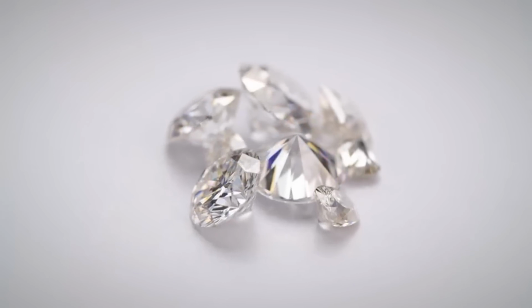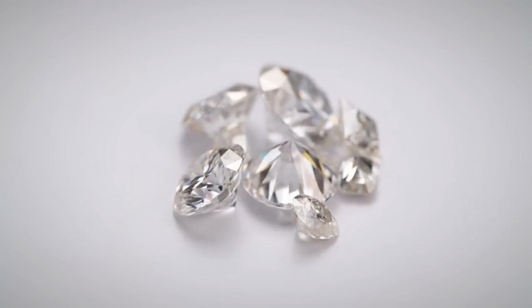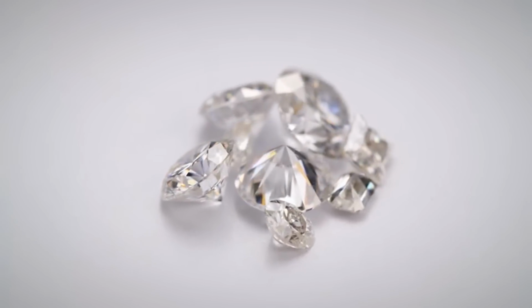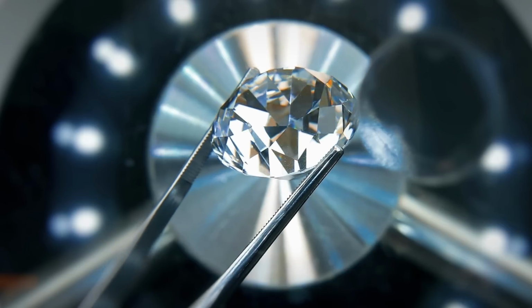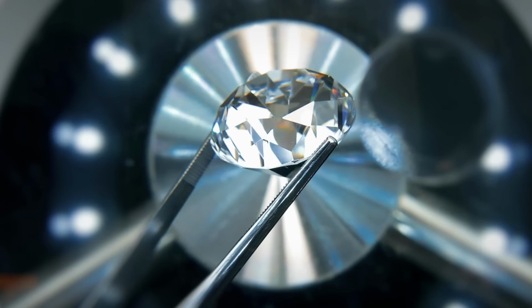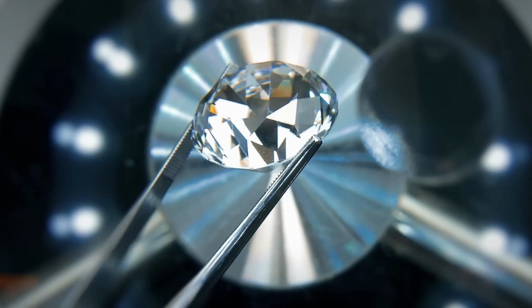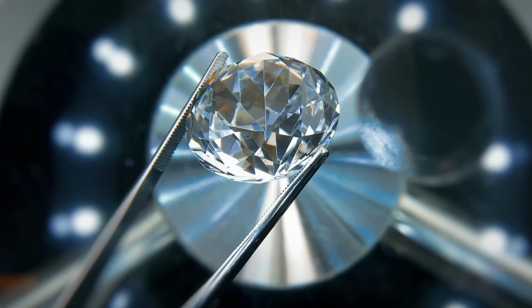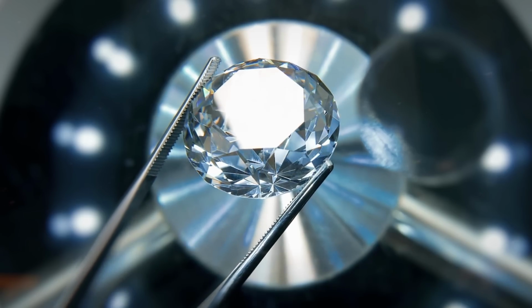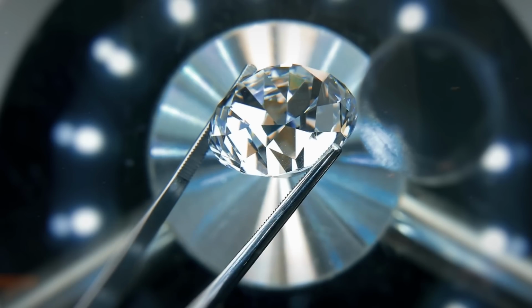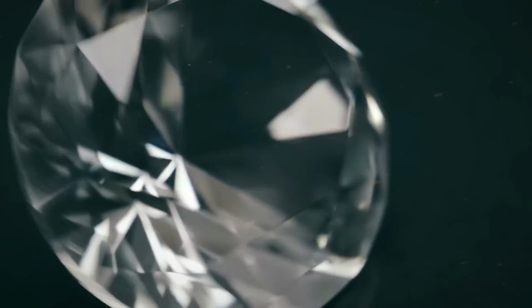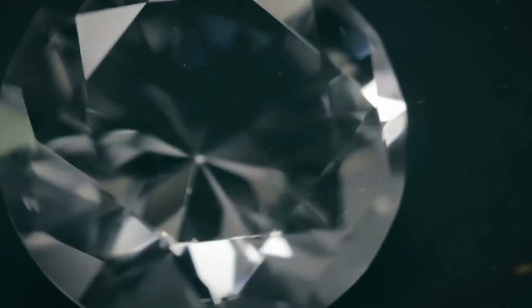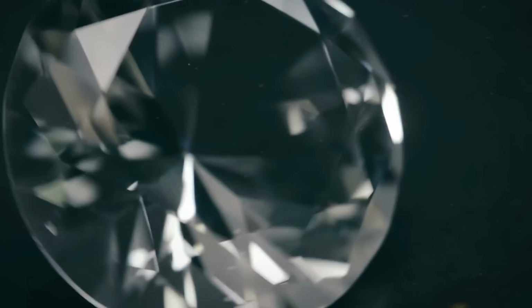Test known samples, quartz, glass, zircon, synthetic moissanite, under the same conditions and compare behaviors side by side. Thermal response, weight in hand, luster under sunlight, loupe inspection for facet doubling. All should be repeatable. If your candidate diverges from known fakes in multiple dimensions, it climbs the ladder of credibility.